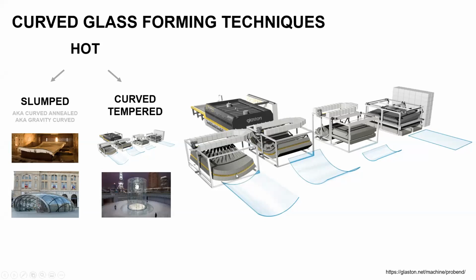You basically, through all of those little nozzles, locally blow air onto the glass, giving it a very, very fast cooling rate. Again, we're going from the order of magnitude, don't quote the numbers, of 1,000 Fahrenheit down to room temperature very, very quickly. As a result, that quick cooling provided by the quenching of all of these nozzles is providing that temper to the glass. And the reason why you need to rock it is you want to make sure you don't have static glass under a local nozzle, because you might have some local stress concentration, which you don't want for the structural performance of your panel, but also visual deformation due to those localized quenching marks.